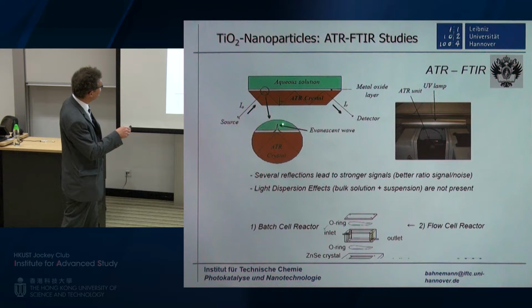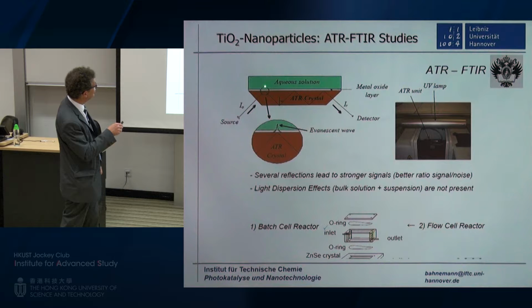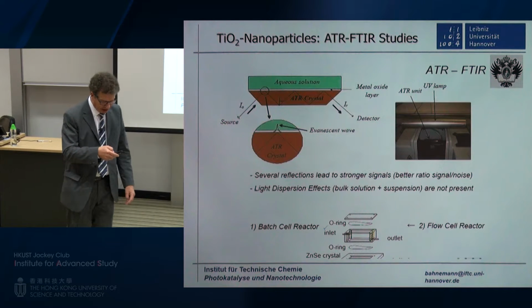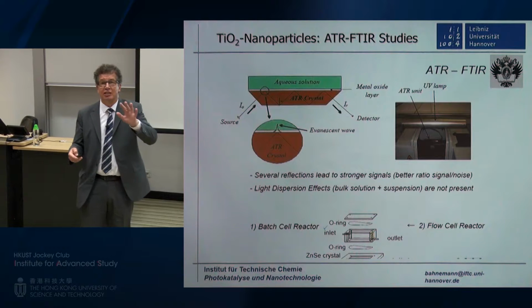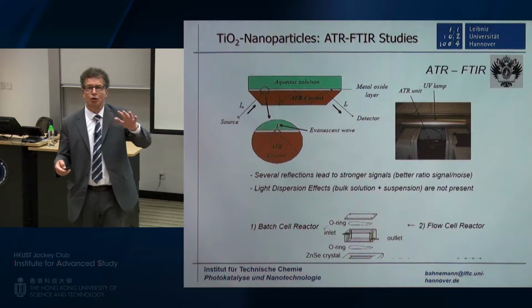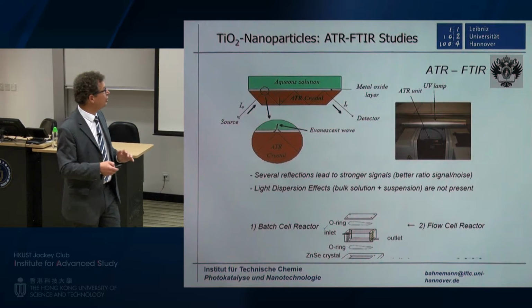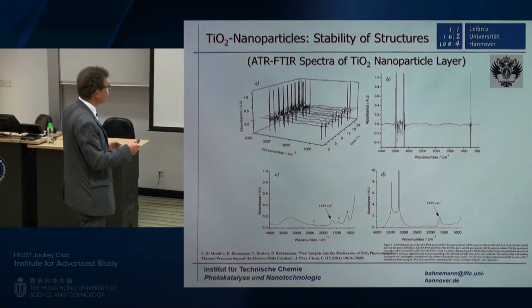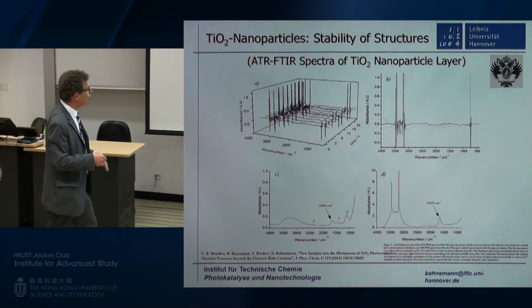And if you look more closely, and this is now the layer of your TiO2 nanoparticles being in the order of a micrometer thick, and on top of that you have the aqueous solution, and actually it is this evanescent wave of your infrared probing light that penetrates through the TiO2 layer and through the water layer, and that can be utilized to probe what's going on at this interface water and TiO2. And we did this, and the blank experiment was just having nothing else in the system, no other molecules, nothing, just pure water. And what you can see is, yes, you can see the adsorption of water on the surface.